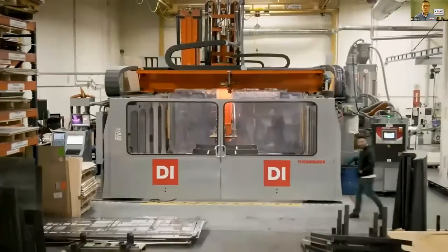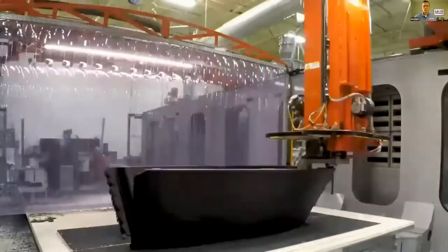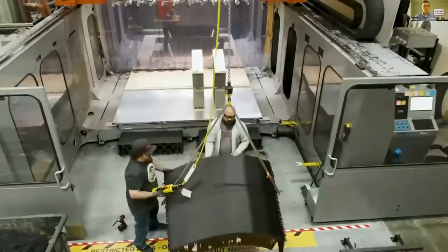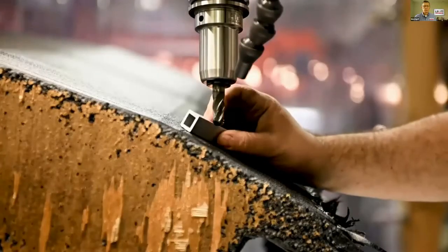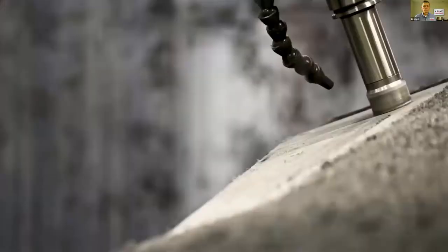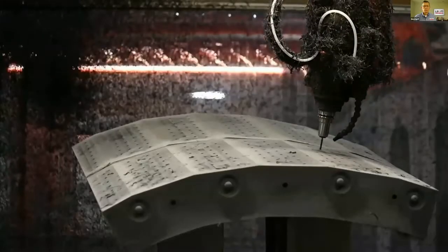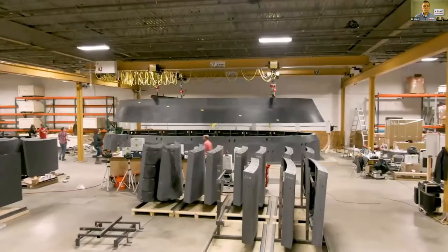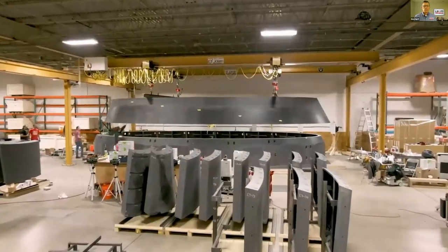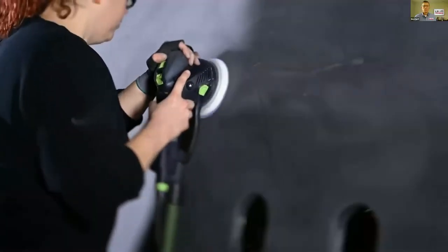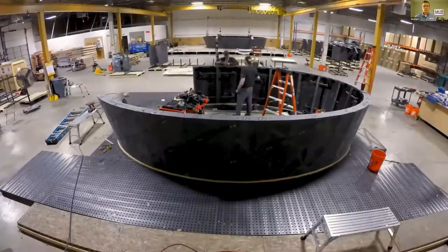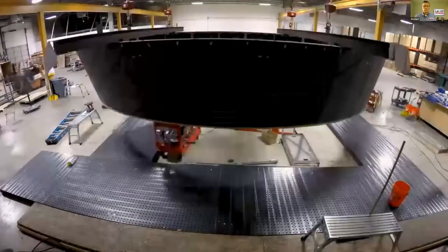But once we got it dialed in, we were printing 2 unique 350-pound blocks a day, and then machining each one to a tolerance of within plus or minus 5,000ths of an inch. Then we drove them down the street to a big warehouse where we checked fit, sanded for final finish, applied protective coatings, and made sure everything would go together perfectly on site. And they did.